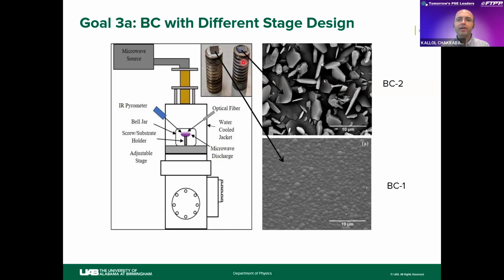More interestingly, when the substrate was sitting on a flat screw, we can see some amorphous nature. And when the substrate was sitting in a screw with the insert, we can see a highly crystalline structure. So it was a more interesting result, because by changing only the stage design, we can control the degree of crystallinity of our synthesized boron-rich boron carbide.